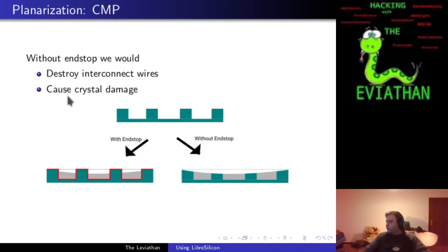It's important to note that you also have to take into account edge effects on wafers. The planarization will never be 100% even, but more in a concave shape, because the force distribution from the center towards the edge goes down towards the edge. So you have to calculate enough thick nitride and enough oxide to have an even distribution with tolerance ranges, so that you can compensate for the edge effects.